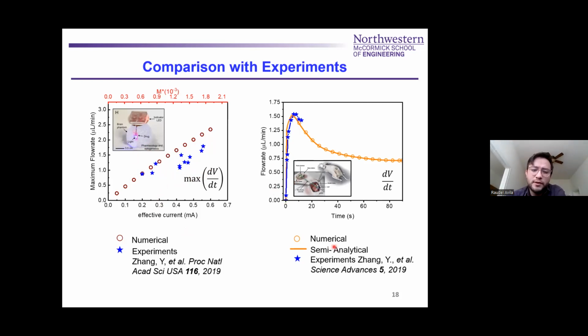But if we take a look at the flow rate versus time, that's just recorded from the experiments until the point of the maximum flow rate, which is the quantity that they care about, it matches very well. This is for a current of about 0.3 milliamps. So this modeling experiment right here, we have very good agreement, particularly at those initial times where the maximum flow